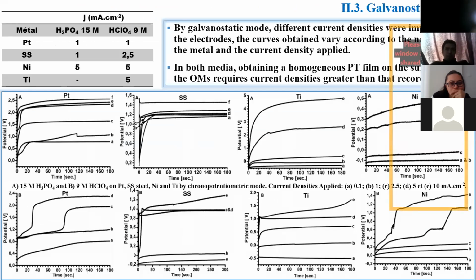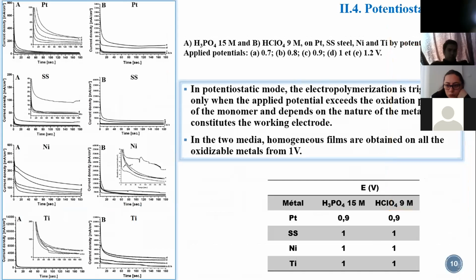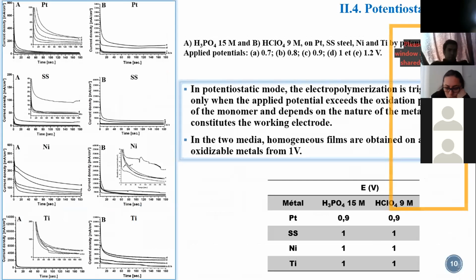In galvanostatic mode, different current densities were imposed on the electrode. The curves obtained vary according to the nature of the metal and the current density applied. In both media, homogeneous polytryptophan films were obtained on the surface of the oxidable metals, requiring densities greater than that recorded on platinum. In potentiostatic mode, the electropolymerization is triggered only when the applied potential exceeds the oxidation potential of the monomer and depends on the nature of the metal. In both media, homogeneous films are obtained on all oxidable metals from 1 volt.